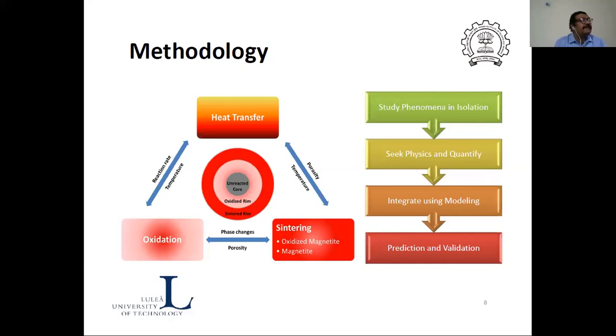So if you have so many phenomena happening, the scientific way of doing things is, you first look at one problem and understand this behavior. If you can isolate that particular thing separately, without having the other things, then use the modeling approach to integrate. This is what I was trying to tell you, that once you understand, and then you do very focused experiments, then one can do a much better job than doing a blind experiment. So that's exactly what I have written. Study phenomena in isolation, seek the physics, that means through experiments, then you try to quantify. This is also very important. We need to quantify this, and then use the modeling principles to integrate, and then you can do the prediction.